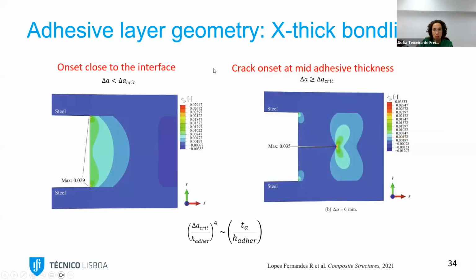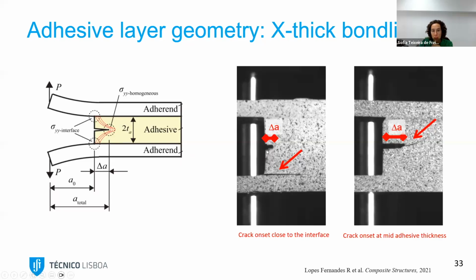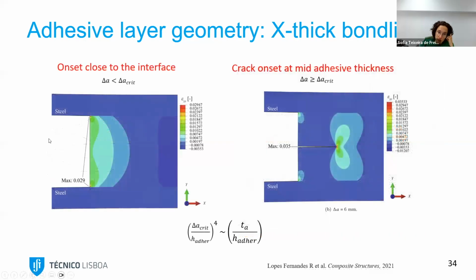And you can also see this in the finite element analysis that we performed. What we found out, and it's quite understandable, is that it's related with this delta A. So for delta A's which are smaller, the stress concentration is not enough here and the crack deviates to the interface. If the delta A here is long enough, then these regions here lose their stress concentrations and this becomes the predominant crack tip. And we can see also in the finite element analysis that we performed, here I show two extreme cases, here without any initial crack length, in which you see indeed that the strains are higher at the interfaces. And after a certain delta A, which we call delta A critical, the stresses are no longer predominant here, but the crack will propagate here at the crack tip.